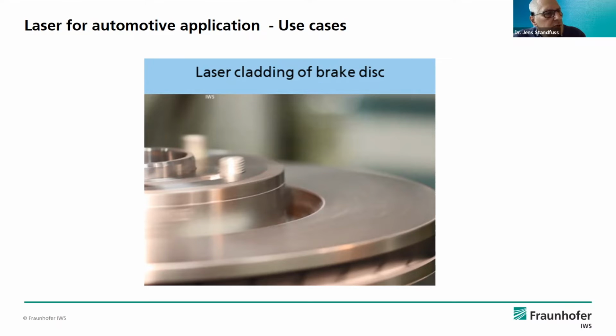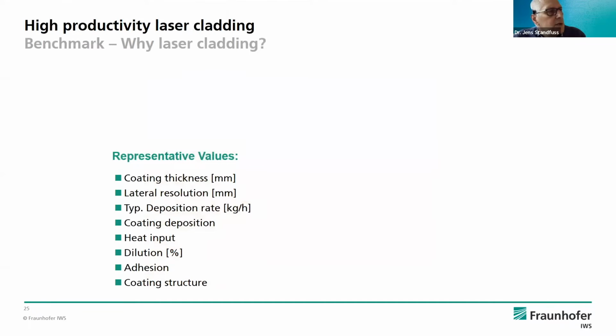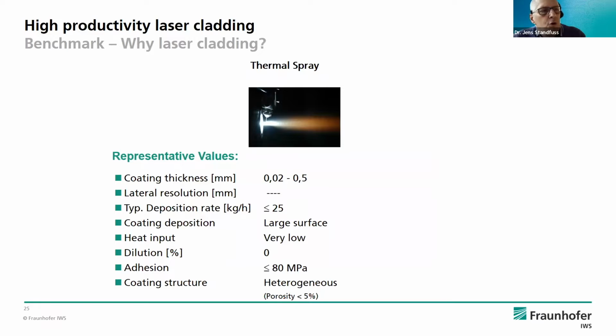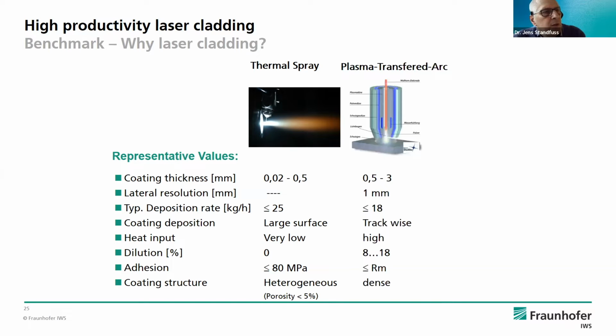Laser is one possibility, but why laser? What is the benchmark for other processes? Thermal spraying is one side. You can have a very thin coating thickness. You can do this for a large surface. You have a very low heat input, but the coating structure is quite heterogeneous, and the adhesion of the coating to the substrate is quite low.